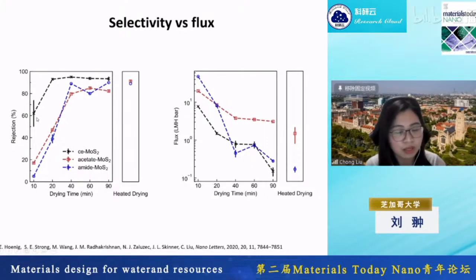And when you are trying to seal up this water pocket and the 2D channel properties start to show up, you do get a very high rejection of the sodium sulfate salt we tested here. But what's disappointing is that because of the drying process, you are actually sealing up a lot of the channels and they just become a dead end, permanently restacked onto each other. And that's not what we want.